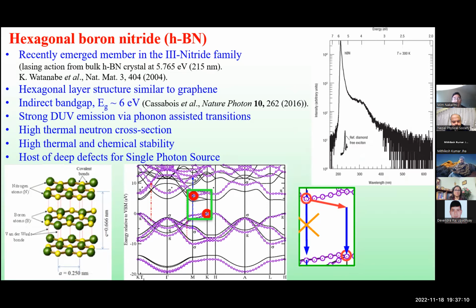most people working on wide bandgap semiconductors started looking at that. And one puzzling thing was the theoretical calculations. They indicated that this material is not a direct bandgap material, but experimentally it shows it can lase at 215 nanometers. That means it must be direct bandgap. So after lots of people, there was even some controversy, where some people claimed it's a direct bandgap and some people claimed no, but none of the theoretical calculations say it is a direct bandgap.